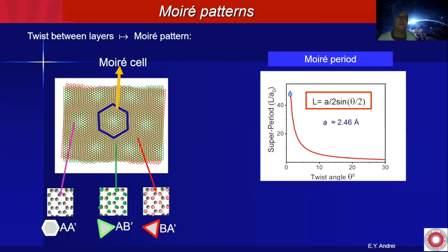Basically, this is an interference pattern. The bright spot here corresponds to positions where the top layer atoms are perfectly aligned with the bottom layer. So the top layer atom eclipses the bottom layer atom. We call that AA stacking. The dark regions are ones where the top A atom sits on a bottom B atom, and the top B atoms have no neighbor, and vice versa in the BA region. So this is how we create this Moiré pattern.